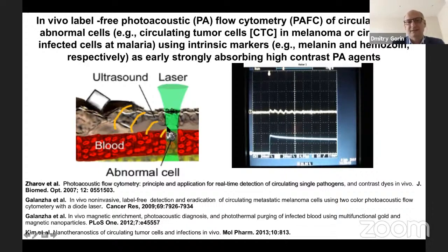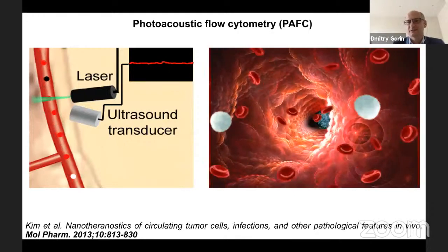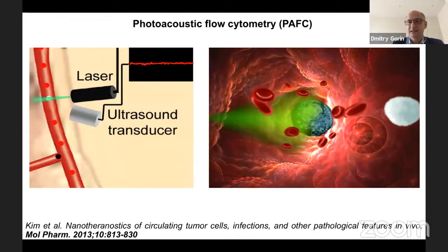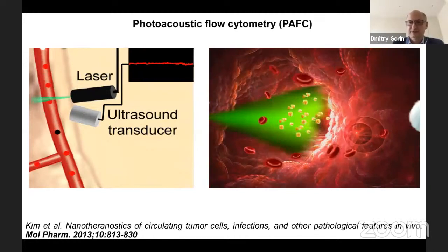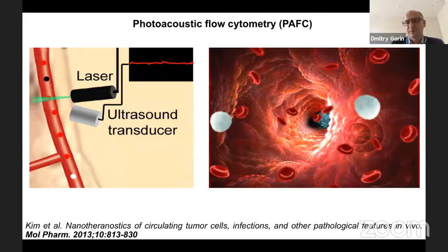And therefore, it's an advantage of this method that we can analyze, for example, 30 minutes just by irradiation of this vessel by laser, and we can analyze approximately up to 1 liter of blood. And of course, it's not possible to take such an amount from a patient for analysis, and therefore it's a promising technique. And other possibilities that our colleagues also demonstrated in vivo, but using animals, is that it's possible by light also